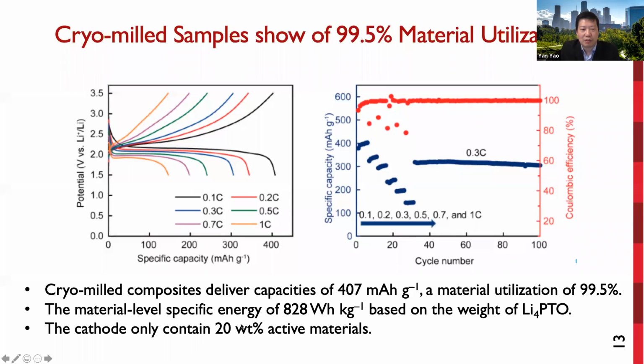So the material level specific energy also reached 828 watt-hour per kg. This is only the material level, not the full cell level. But nevertheless, this puts it among the best solid state chemistries and shows the potential for organic electrode materials in enabling high energy batteries. The cycling performance of the cryo-milled sample is also very good.